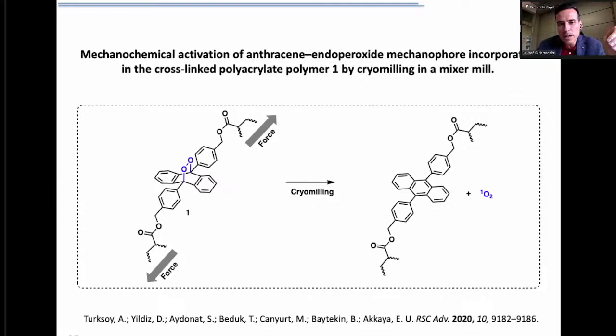What they observed was indeed the release of singlet oxygen, and also the transformation of the original polymer into the anthracene-containing polymer. So the question here was, is it really this reaction promoted mechanically? And for addressing that question, the authors carried out reactions at cryo temperatures. And they demonstrated that even at such low temperature, the polymer was undergoing the mechanochemical reaction by milling.